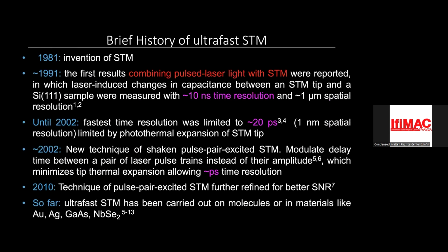And this idea that you can use light to get time resolution is actually really old. In fact, this is just a brief history. Within 10 years after the invention of the first SPM, people started thinking about how to use light to get time resolution. And so they realized that you can combine pulsed laser light. And in fact, the first results were reported in 1991, where they got 10 nanosecond time resolution. Now, nanoseconds is not fast enough. Nano seems really fast, but 10 nanoseconds is simply not fast enough to capture dynamics. However, this was a really great first step.